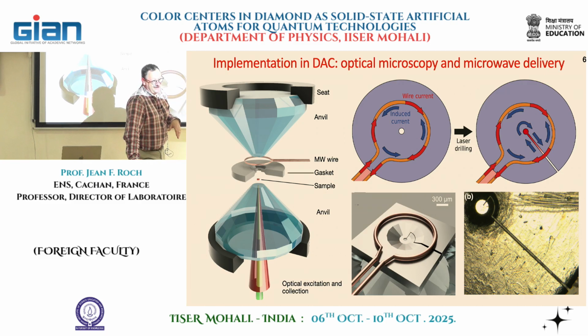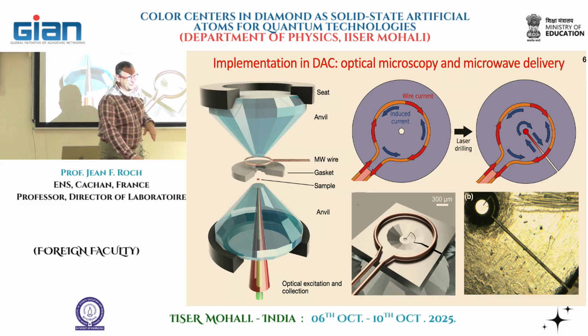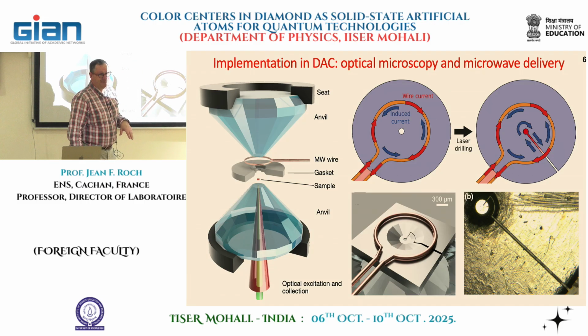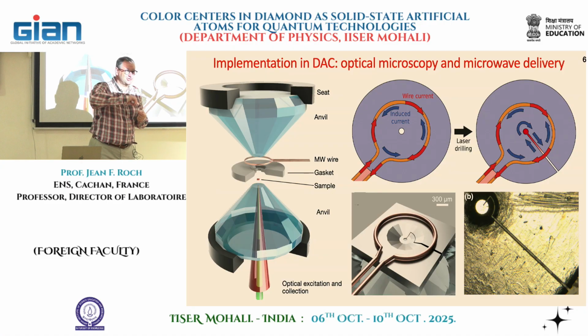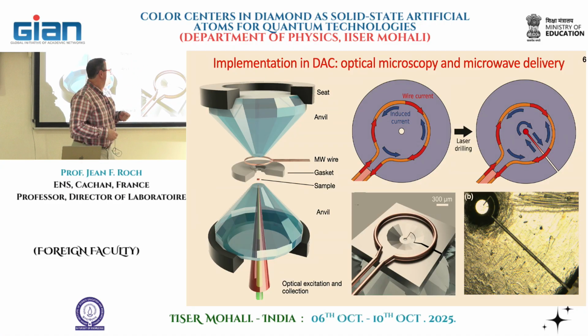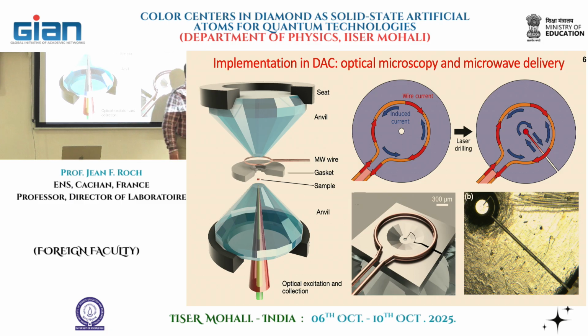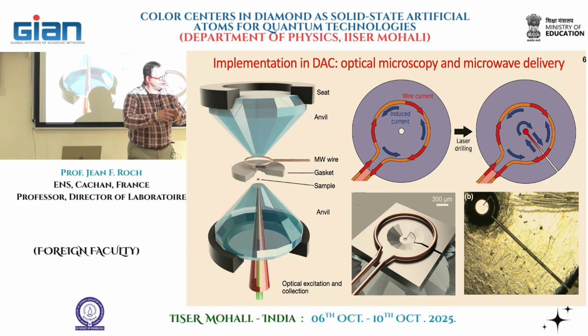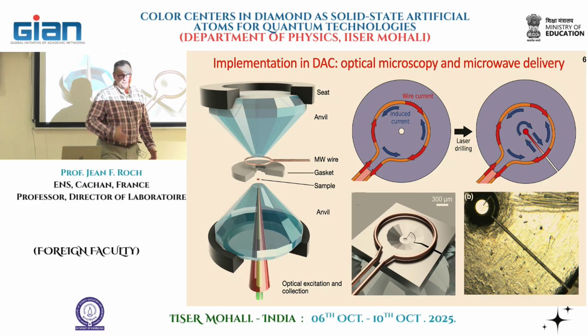And actually, we were very proud of that idea, and we found that it was also already invented a few years ago by Ike Silvera at Harvard. Nevertheless, this simple idea worked. We were happy about that, and then we thought a little bit again, and we found that the slit was acting in a way more subtle than we thought, because somehow the eddy current will be redistributed, and close to here, you see that they turn the same way as the current in the coil. So somehow it's a way to focus the microwave excitation.